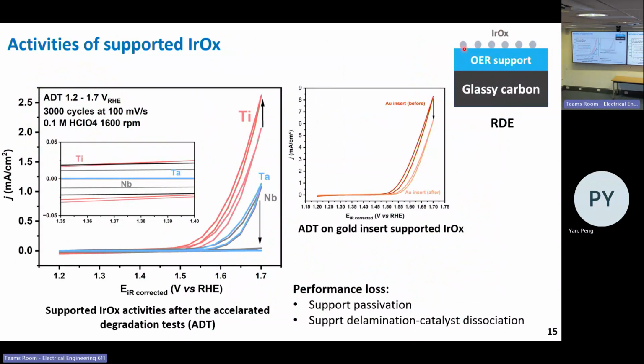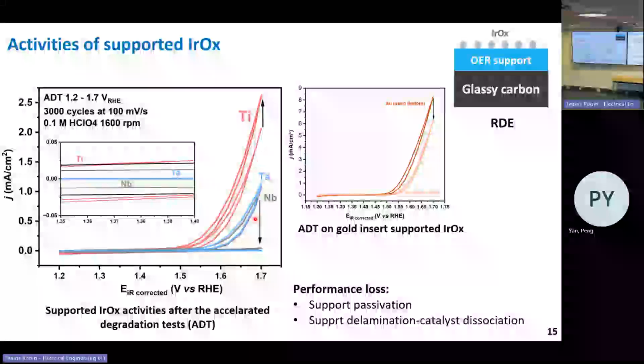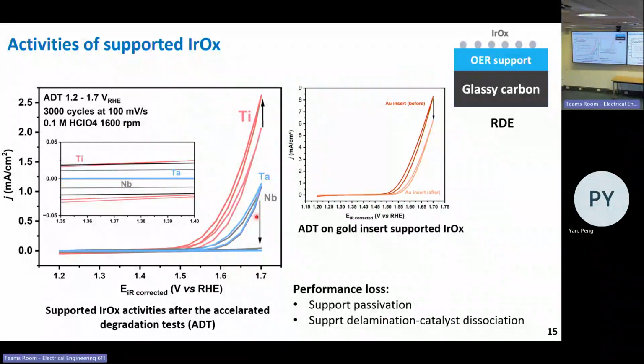Iridium oxide was then drop cast onto titanium, tantalum, and niobium films. And after accelerated degradation test, only titanium was able to sustain the activity of iridium. There's no activity at all when supported onto tantalum and niobium. This result confirmed the suitability of titanium to be used as the OER support.